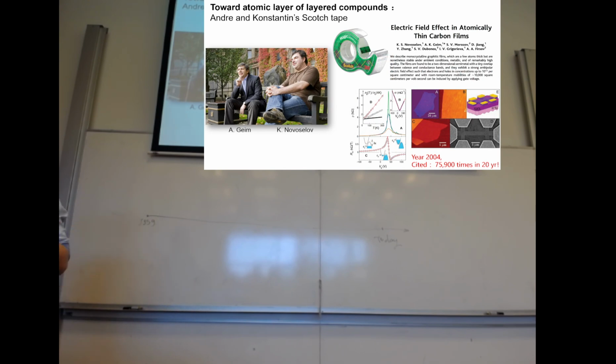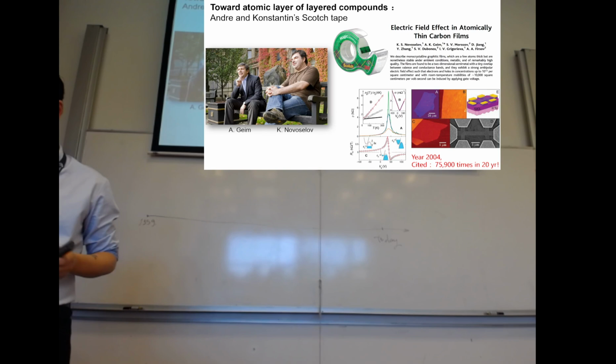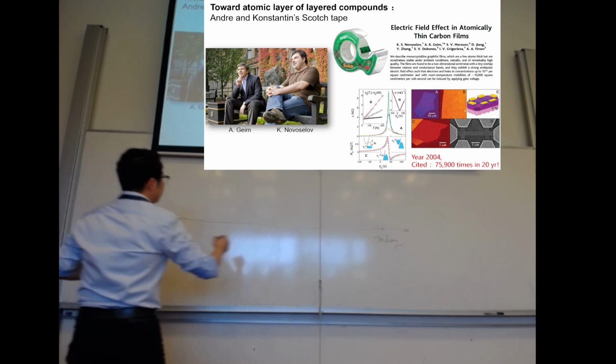They didn't do any screening. They didn't choose that on purpose. They just grabbed one from their old stock on the shelf of their lab. We have this wafer, let's give it a try. And at the end, we got very thin films that we can see with bare eyes directly. And if you choose, for example, a 200 or 500 nanometer thickness silicon oxide wafer, you will have missed it. So that's how it was discovered in 2004. Already here.